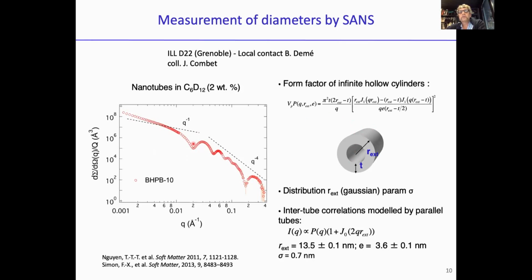And these curves could be described by the theoretical form factor of infinite hollow cylinders, as you can see here. And it depends on two parameters. The first parameter is the outer radius, and the second parameter is the thickness. And we can fit this very nicely. So this is a theoretical form factor. And you can see all these series of oscillations here. And in fact, we have to take into account the experimental resolution. And from this curve, we are also able to measure polydispersity, a variation in diameter that we've introduced here with a Gaussian distribution. And so we are able to measure this parameter.